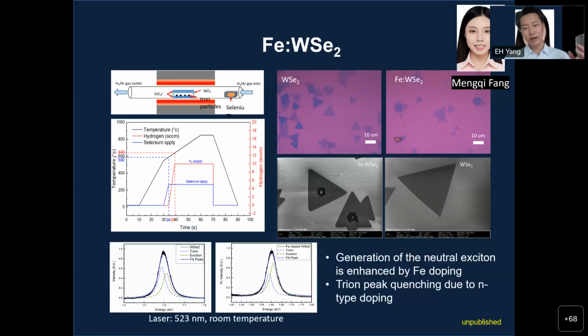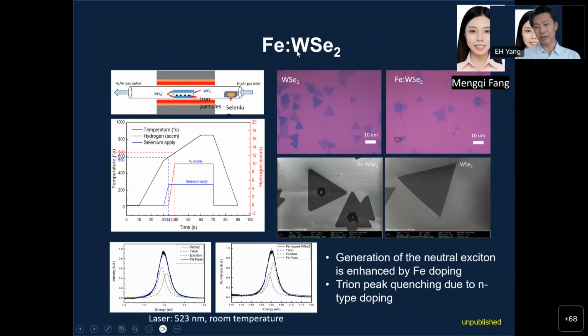Now, what if we directly dope iron into tungsten diselenide instead of using iron doped molybdenum sulfide and the magnetic proximity coupling? Then probably we'll get a quantum emitter with magnetic property from this material alone, right? So that's what we try here. I mean, we haven't made the quantum emitter from this yet, but on the left, it shows the detailed